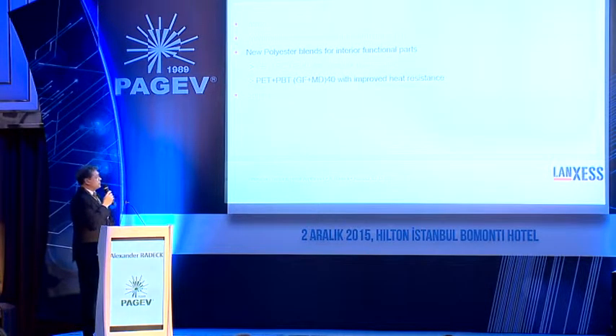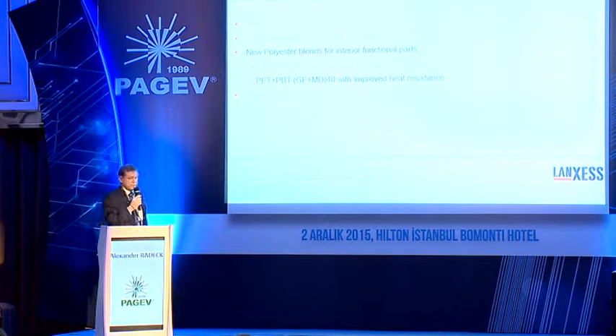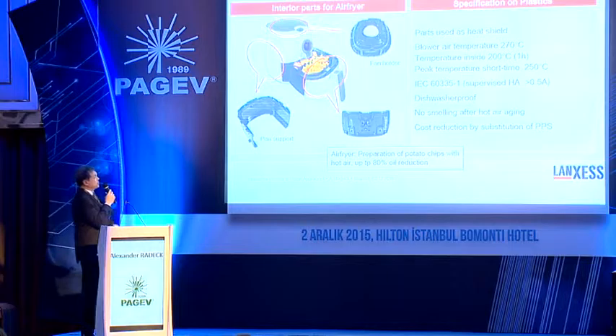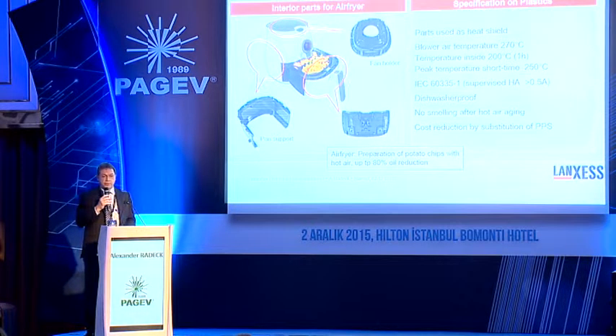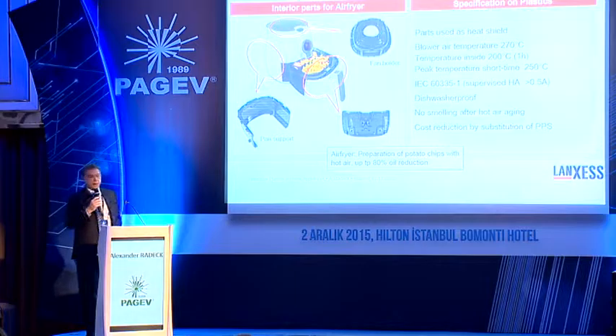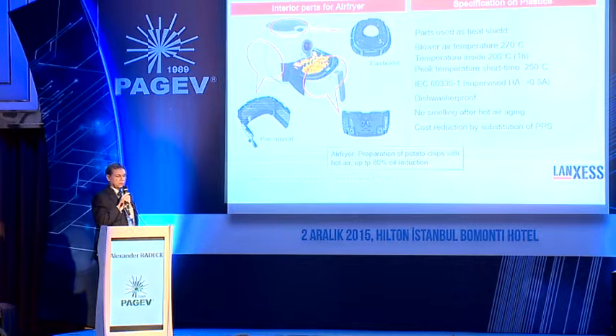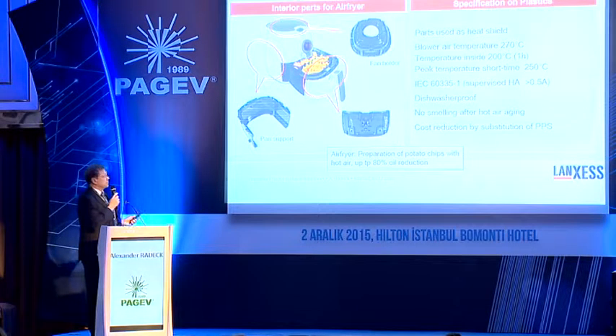The next sample is a polymer blend with improved heat resistance based on PET PBT, and here I chose an example of an interior part for an air fryer. These parts are used as a heat shield for the outer housing made in polypropylene. You see here the temperatures in the device under service. You have 200 degrees over a longer time, 1 hour, but you also have peak temperatures of up to 250 degrees Celsius. These parts had to pass of course the IEC 60335-1, and this application is seen as supervised household appliances.